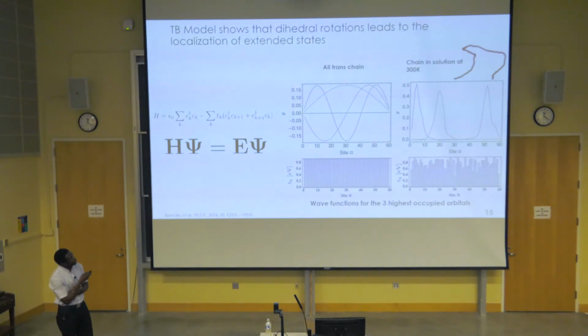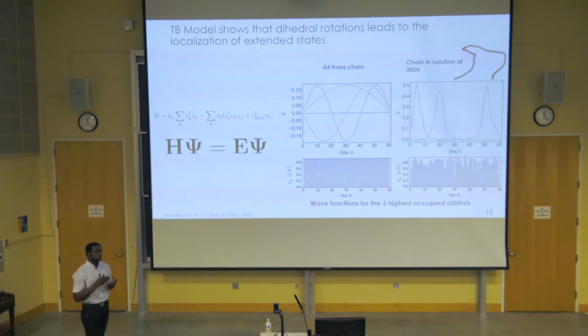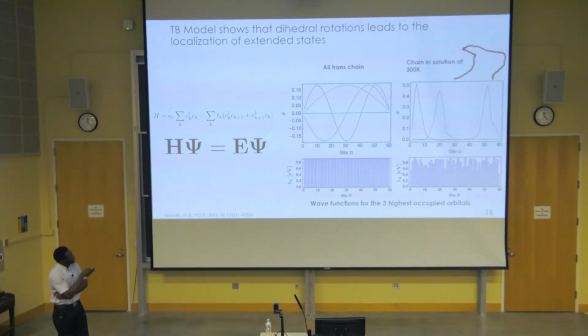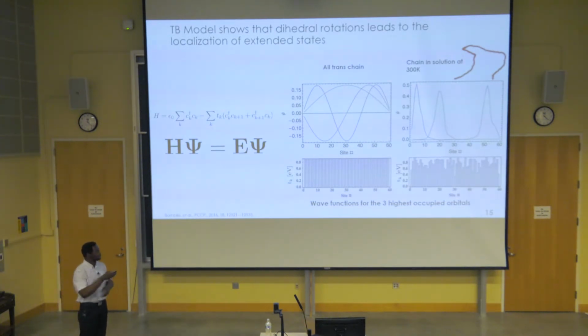We look first at perfectly ordered chains. So that would be a chain devoid of any dihedral distortion. And within such a chain, what we found is that the highest occupied electronic states are delocalized over the whole chain. This is the wave function, and the best way to understand the wave function is that when you take the square of the wave function, you get the probability of finding the particle in space. So this extended wave function gives us an idea that the charge carrier will be delocalized within such a chain.